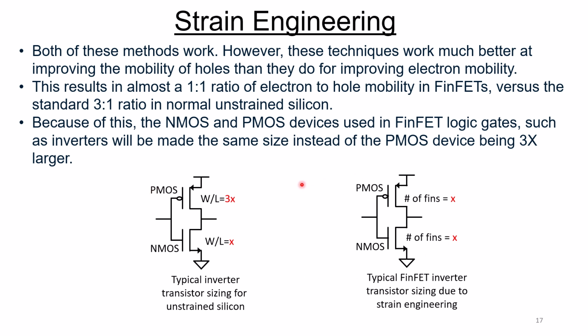And here we show this in a pictorial form here. Here we show a typical inverter with transistor sizing in an unstrained silicon process. And typically the PMOS device, the W over L ratio, would be about 3x that of the NMOS device. And again, that's to make up for the 3-to-1 difference in mobility of holes versus electrons. However, over in a FinFET device, typically what we're talking about is the number of fins used in the PMOS device and the number of fins used in the NMOS device for an inverter would be identical, because due to this strain engineering, the mobility of holes is almost identical to the mobility of electrons.